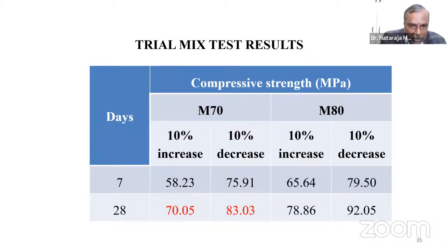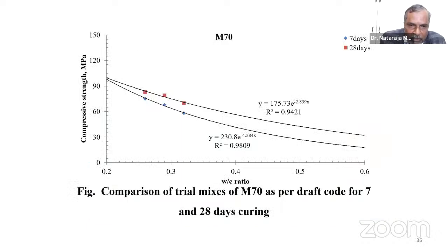And compressive strength for 10% increase or even 10% decrease. So you can see, and finally you can draw a graph and you can appreciate. So this is the final graph that is very, very important from the point of subsequent concrete mix design. And even now, using the same set of materials, even if you want to design an M50 concrete or an M60 concrete, determine the target strength and pick up the water cement ratio, either for the 7-day requirement or even for the 28-day requirement. And your further concrete mix design will become very, very easy with these graphs being developed.